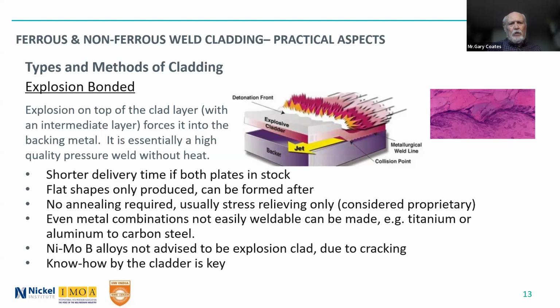One of the key factors, you don't need to anneal them after, but you usually do a stress relief. As you can imagine, there's a lot of stresses involved in this process. And I know in talking to various explosive cladders that the stress relieving is a proprietary thing. You really can't get out of them exactly what they do, what temperature they actually stress relieve at. And it is one of the secrets, one of the know-how components of making clad. And each combination of material will usually require a slightly different stress relieving temperature.